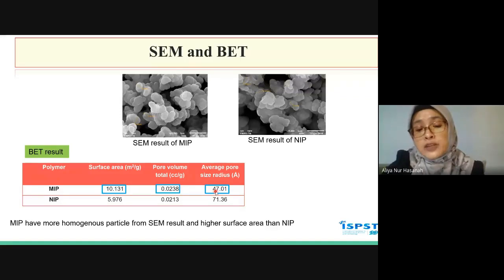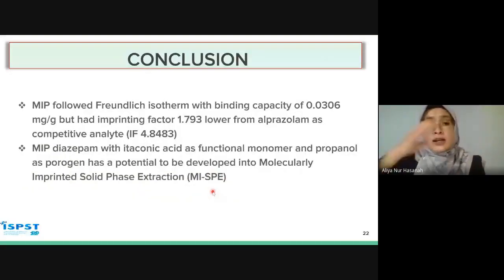The average pore size radius is also smaller, so it means it's good for absorption. It correlates with the result of the imprinting factor, that the MIP is better than NIP. So based on that, we can conclude that the MIP follows the Freundlich isotherm with a binding capacity of 0.0306 milligram per gram, but had an imprinting factor lower than alprazolam as a competitive analyte.